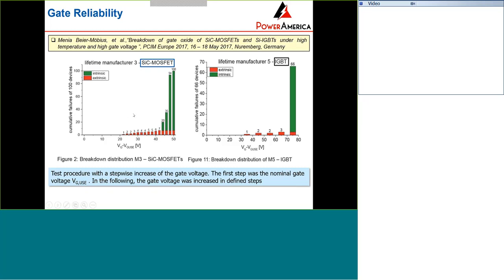You can see that both devices show extrinsic failures, the red bars, when you increase the voltage to some number. For silicon carbide, VG minus VG use is beyond around 20 volts. On the silicon IGBT it is beyond 30 volts. The difference may be attributed to the different gate oxide thickness. Both devices show the intrinsic breakdown voltage at some number. It looks like the silicon carbide trench MOSFET has a higher failure rate, but generally speaking, the silicon carbide trench MOSFET shows a comparable extrinsic failure rate to that of the silicon IGBT. So it's very promising and shows evidence of the gate reliability with the trench structure on the silicon carbide MOSFET.